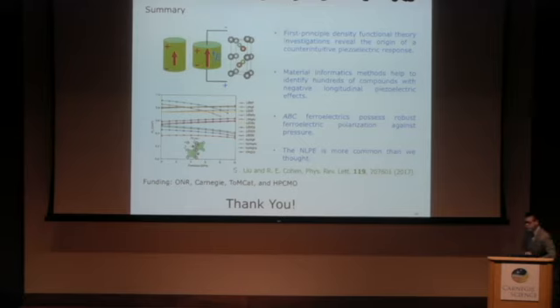Negative dielectric constant, we don't see negative dielectric constant. When we turn on the electric field, the polarization still becomes larger. The strain becomes smaller. So the dielectric constant is still positive. So the coupling between dielectric constant and piezoelectric constant, there is a negative sign, right? It's also negative in this case. Right? Because your PVDF actually shows a positive dielectric constant, but it has a negative piezo constant.